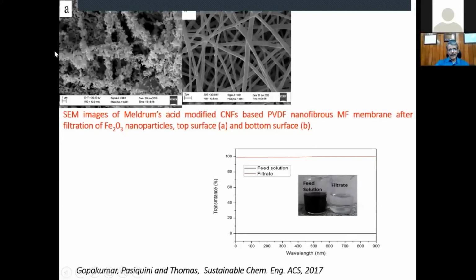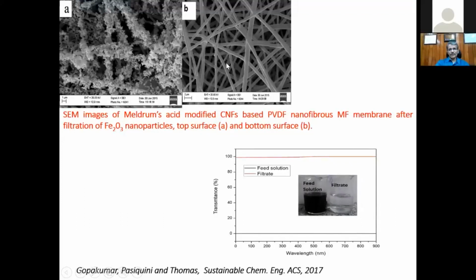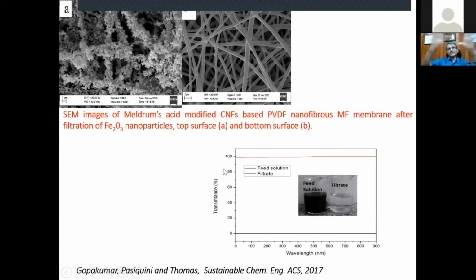You can see all the iron oxide particles have been retained on the top surface of the membrane. This is the bottom part of the membrane. You can see the impure water, and this is the pure water. You can see the transmittance. Impure water, you see zero transmittance. Pure water is almost 100% transmittance.